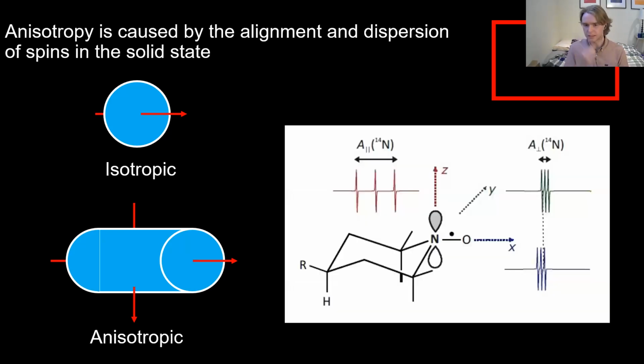So if we think about the example of tempo in this case, again, here is the tempo molecule. Notice that we have our single electron. In this case, it's denoted between the nitrogen and oxygen, which is pretty fair. We have a variety of different measurements depending on the axis of measurement of the molecule. If we were to take EPR in the X or Y frames of reference given here, we'd see that our spectra are pretty similar. There's obviously a little bit of a shift in the spectra, but overall, the difference between the peaks is relatively the same. But if we compare that to the Z-axis spectra, we'll notice that the difference between the peaks is much, much greater. There's a lot more space between those peaks,